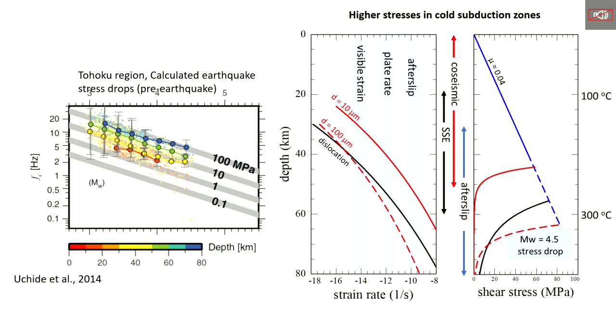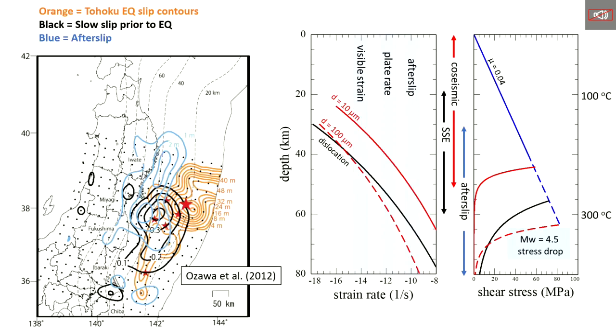By going deeper, the stress is higher. So we can make the strain rate of all of these processes faster at a given temperature because the stress is higher. And as a result of that, one thing that's cool is that a 10 micron pressure solution law can accommodate plate rate at a temperature of like 200 degrees, if you just believe the flow law. And even more incredible is that you can get the strain rate for afterslip all the way down at 50 kilometers.